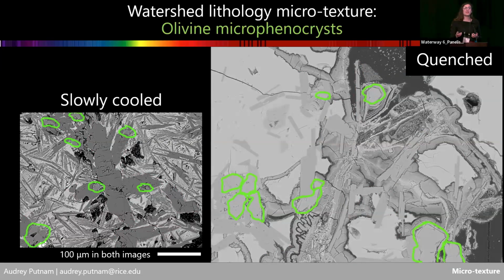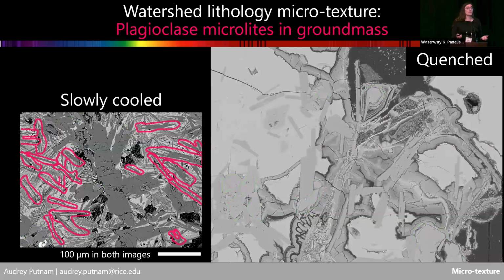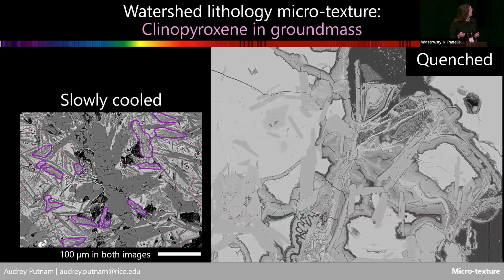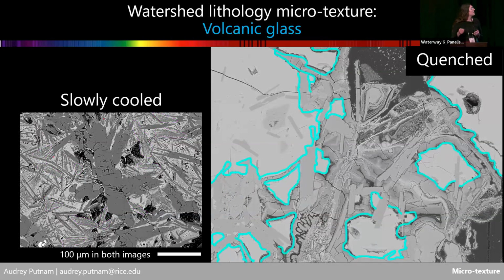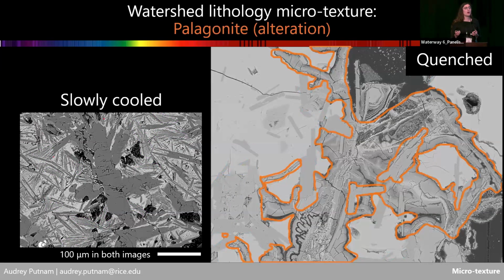The interesting and fun differences is what happens with the remaining melt when these lavas reach the surface. So in this slowly cooled clast on the left, we can see that the remaining melt was allowed to slowly cool into plagioclase microlites and then these nice dendritic clinopyroxenes. Whereas in the quickly quenched clast on the right, the remaining melt was quenched into volcanic glass, some of which has been hydrothermally altered into palagonite.